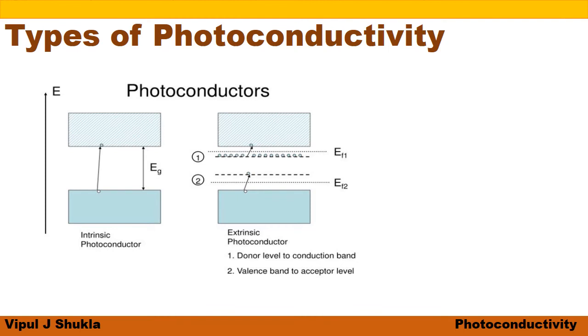Therefore, the transient photocurrent response rise time is due to the desorption of oxygen, whereas the photocurrent fast fall is due to the transit time taken by the carriers, which is inversely proportional to the electron mobility and bias voltage.